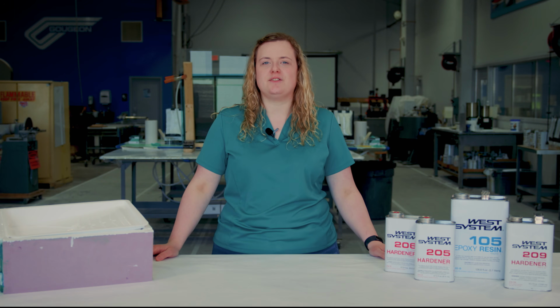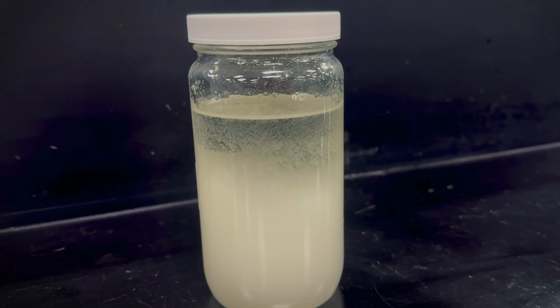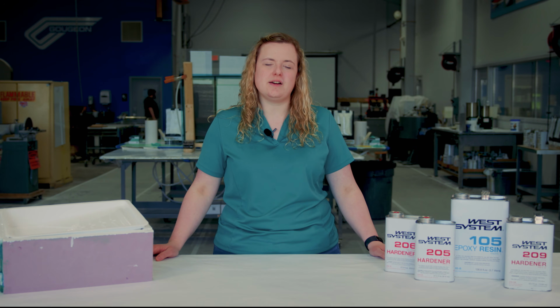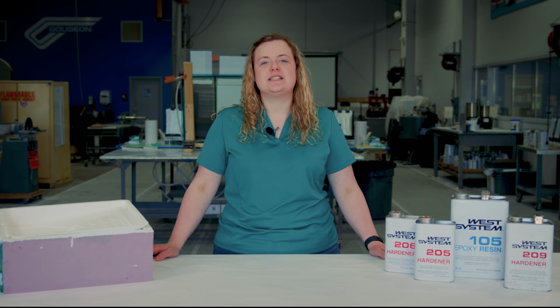Although it's rare, our 105 resin can crystallize, especially when temperatures fluctuate around 50 degrees Fahrenheit. The good news is, those crystals can be redissolved by heating the epoxy to about 125 degrees Fahrenheit and stirring occasionally. Once all the crystals are dissolved, you can still use the product for structural applications.